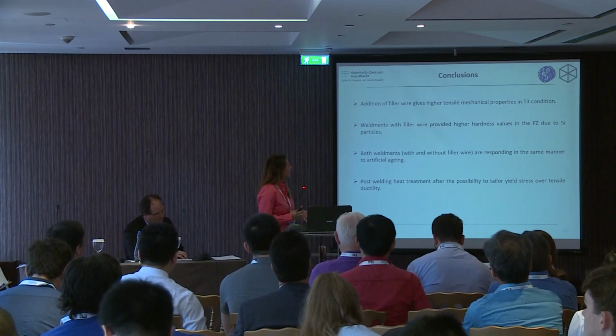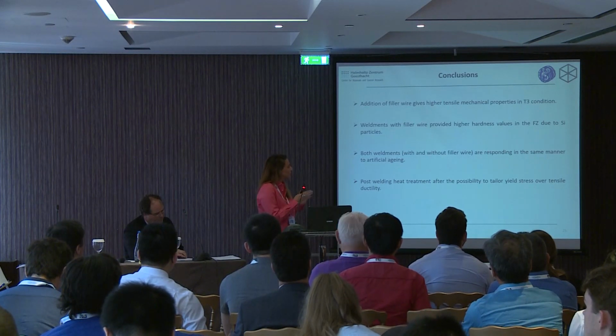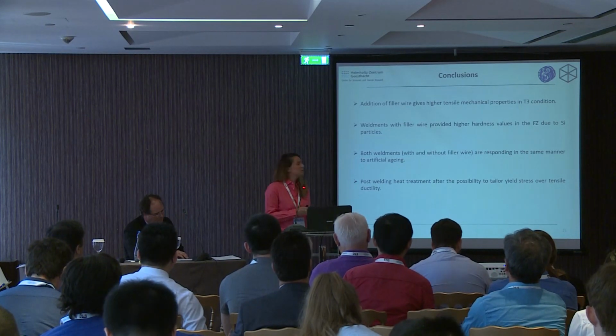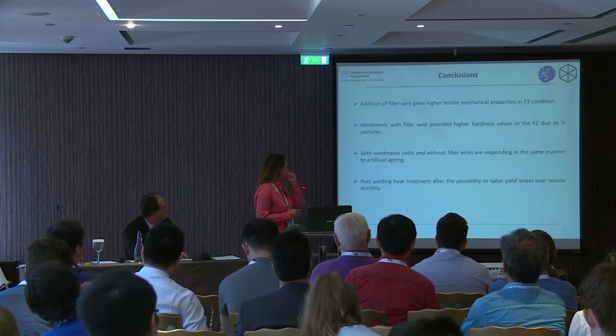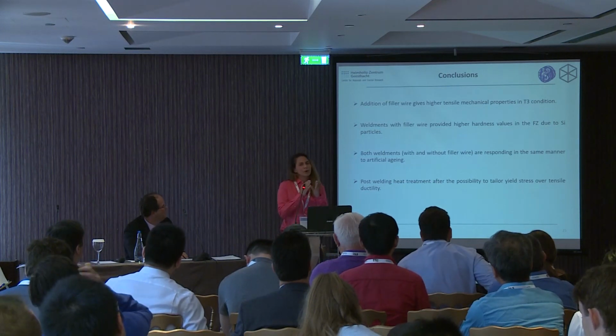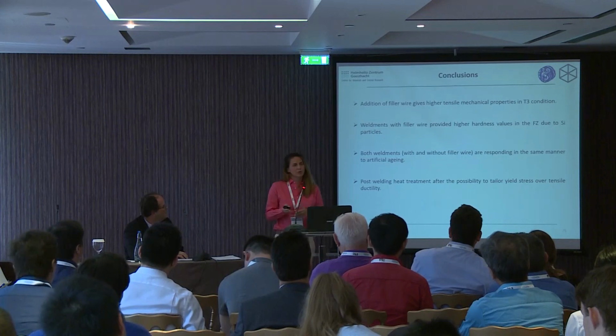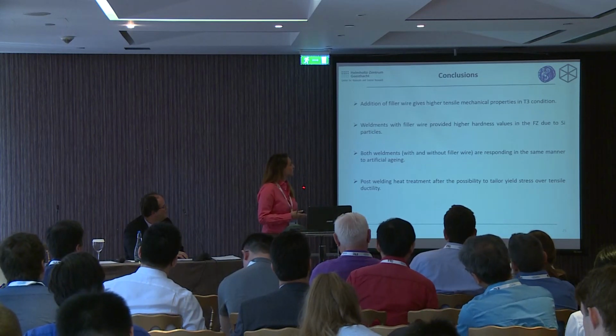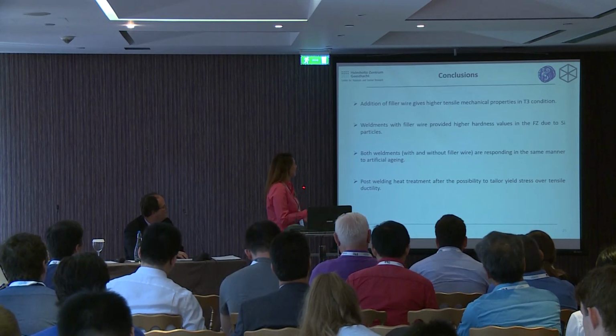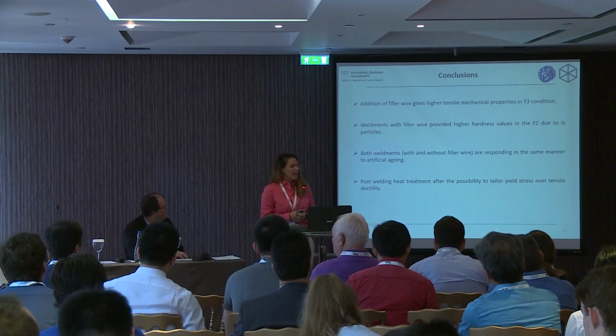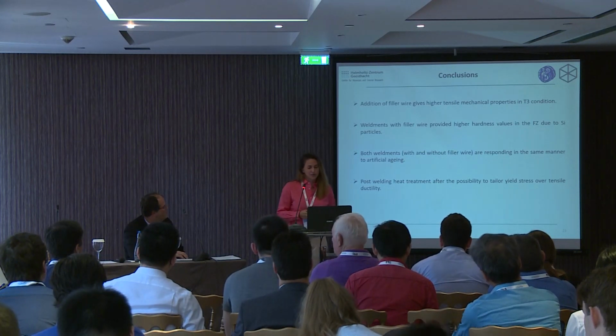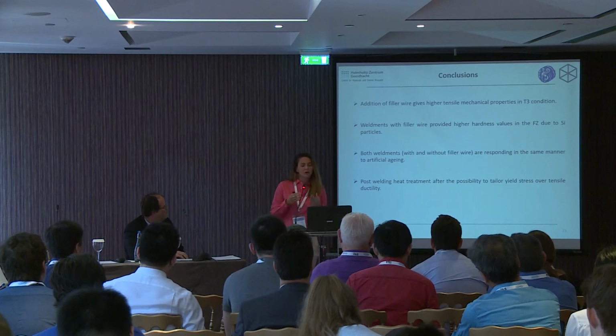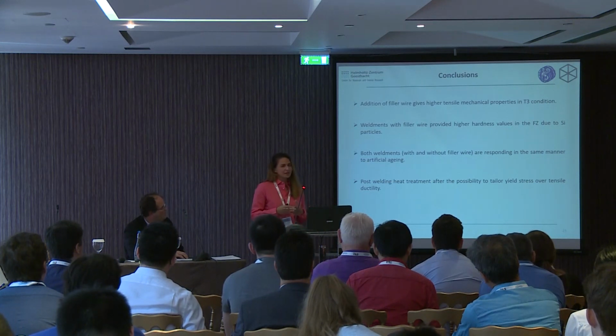Weldments with filler wire provide higher hardness values in the fusion zone due to the silicon particles. Both weldments, autogenous and with filler material, respond in the same manner to artificial aging. And post-welding heat treatment offers the possibility to tailor yield stress over tensile ductility.